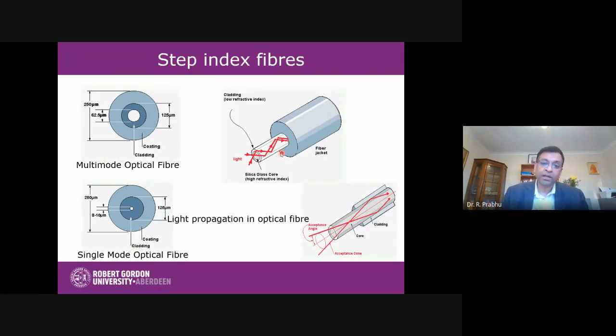From the structural perspective, you have the core with high refractive index and the cladding with slightly lower refractive index material. If you look at the cross section of this step index fiber, it has probably around 60 to 100 micron diameter as core and cladding around 125 and above. This fiber is normally termed a multimode fiber because it supports multimodal transmission of light in the fiber. When the diameter of the core reduces to below 10 micron, it becomes a step index single mode fiber, and that is widely used for communication purposes.